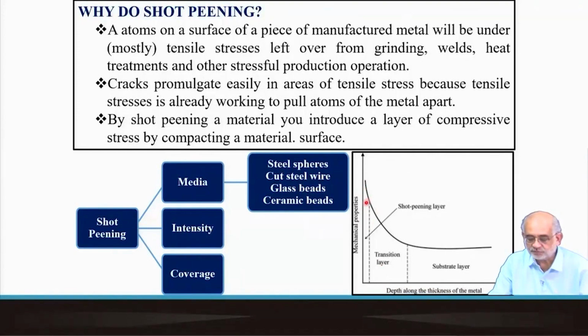So the properties are confined only within the very narrow surface region, which is the so-called shot peened region. Below that, we have a transition region where the stress will change from being negative or compressive, gradually going deeper inside the material where it could be tensile. So in practice, one can detect a neutral plane where the residual stress will be zero and then becomes tensile. Now, this is applicable not only to materials like a roll or a cutter, it is also applicable to materials or components which are exposed to fairly high temperature.